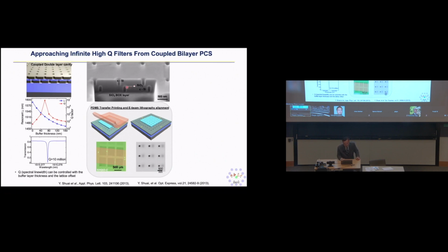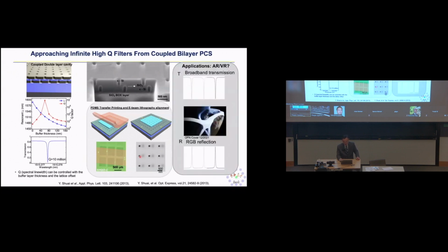This is the FIB cutout. You can see a top crystal silicon, bottom crystal silicon, and a thin oxide layer in between. That's the kind of structure that was made. Here shows the top view of the structure, with multiple devices here. This one shows a zoom, showing the bottom air hole and top air hole here, you can see, with a controlled offset.